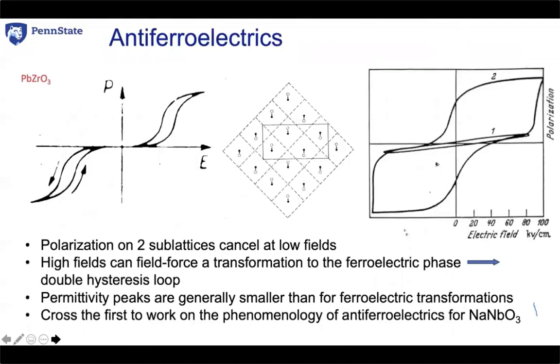Anti-ferroelectricity was also being discovered at this time. Anti-ferroelectricity, of course, entails polarization on two sublattices, which cancel each other out at low field, but under a high enough electric field, we can field force a transformation to a ferroelectric phase with a double hysteresis loop. And as I mentioned, Cross was really the first to work on the phenomenology of anti-ferroelectrics, which he did on the sodium niobate.